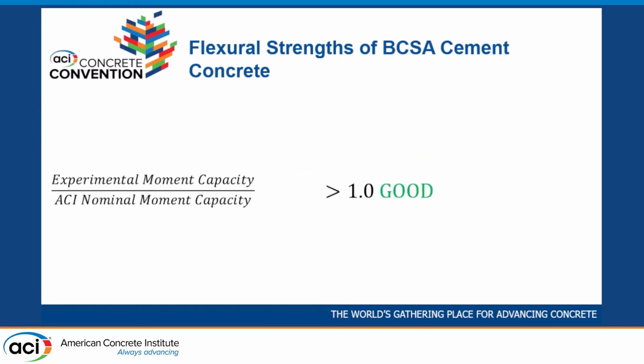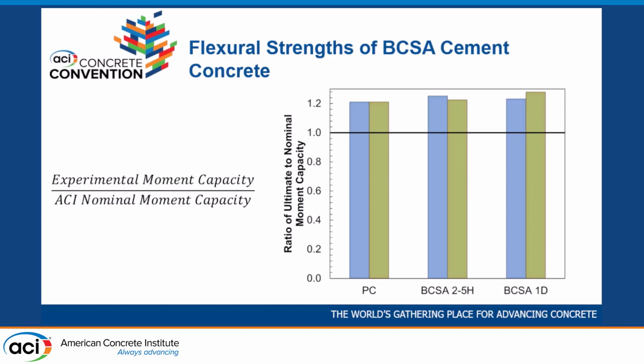So we also look at just moment capacity. We divided the experimental moment capacity by the nominal moment capacity, so greater than 1 is good. And they were all greater than 1. And you can see this ratio is pretty similar for the BCSA beams as it was for Portland cement. So the code equations are just as conservative for BCSA as we would expect them to be for Portland.